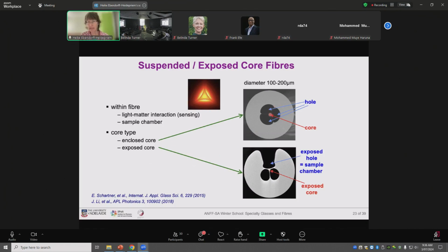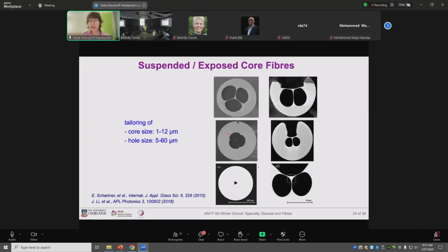So here you have the tiny core in the center surrounded by air holes. Light is guided in this small core. A portion of the light goes into the air holes and can then be used for sensing via light-matter interaction by filling the holes with material. And we can make these types of fibers with different core sizes, and also, as you can see here, with different hole sizes. So we really can adapt them to the target application.